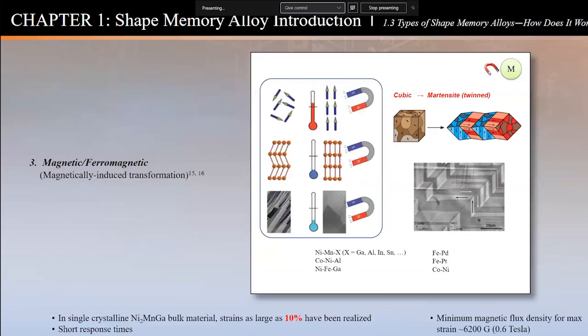There are magnetic or ferromagnetic shape memory alloys, where you can change the microstructure by applying or removing a magnetic field. This could be advantageous where we have a magnet available, or you can guess already that if you have, for example, a shape memory effect, you have to introduce heat and you have to remove heat. That means time. A magnet, you can turn on and off much easier, faster. So this means you can choose one or the other depending on the application.